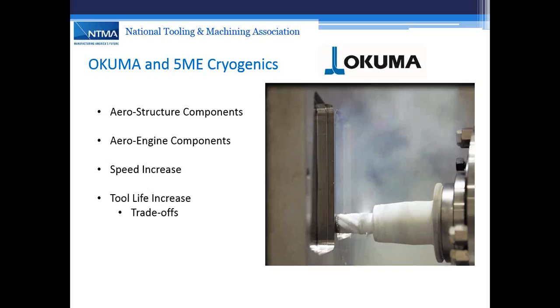As George was saying, by monitoring the spindle bearing temperatures, which is people's biggest concern is the impact on the spindle, we only see maybe a 1 to 3 degrees Celsius change over 8 or 10 hours at runtime. So very low impact on the machine, which is always a good thing.